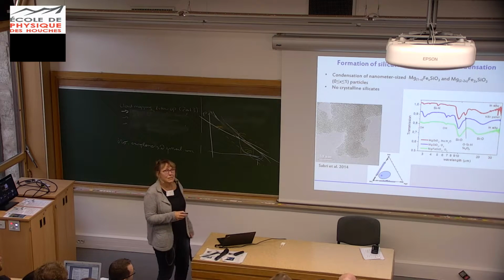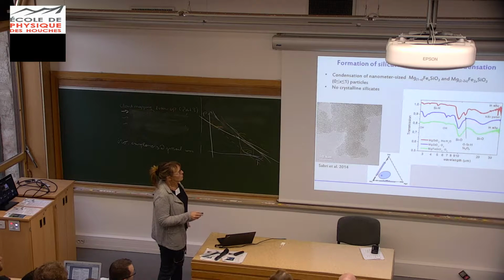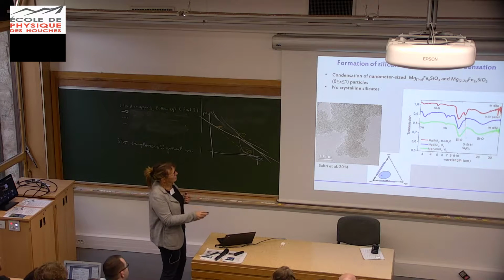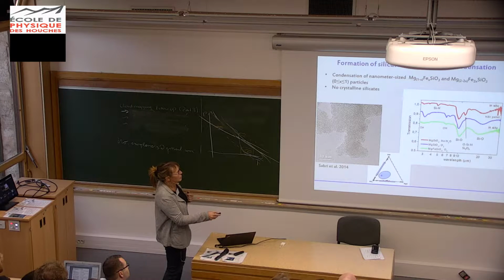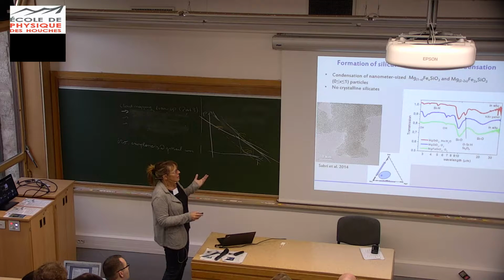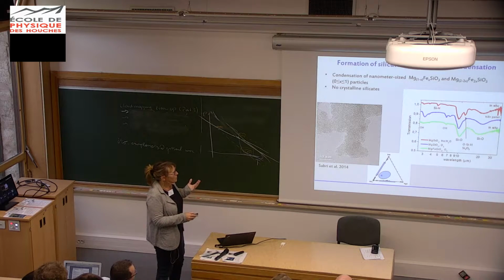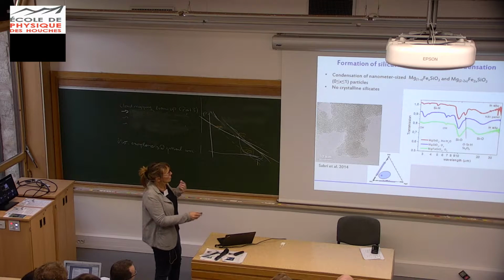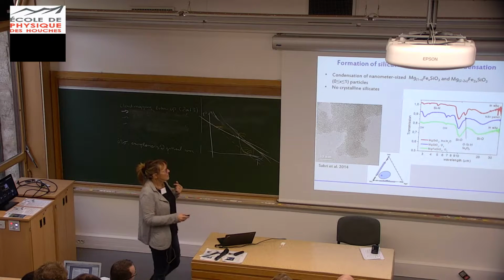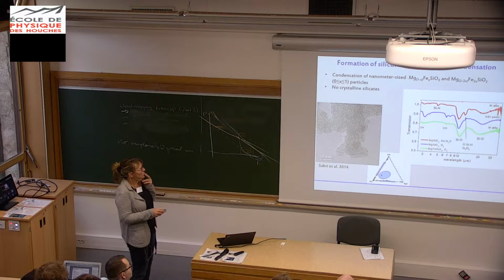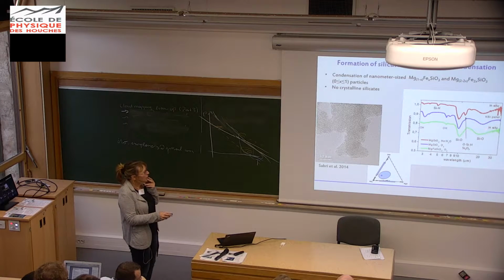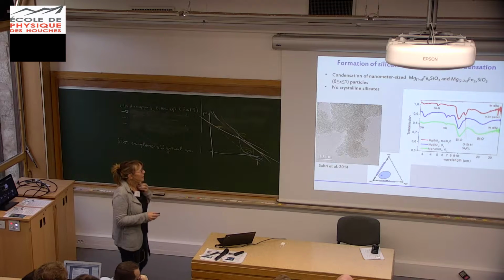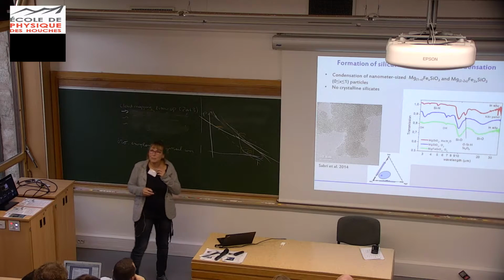I will say something about this on the next slide. However, I want to stress something shown here. You can also produce something amorphous which doesn't have the typical band structure like normal pyroxenes and olivines. This material is amorphous but has some SiH bonds inside - you can see the SiH band at about 4.6 micrometers. Due to this SiH band, you get a slight shift of the SiOH stretching band, and then the appearance of a second band, making it look a little bit like a crystalline material, but it's amorphous.